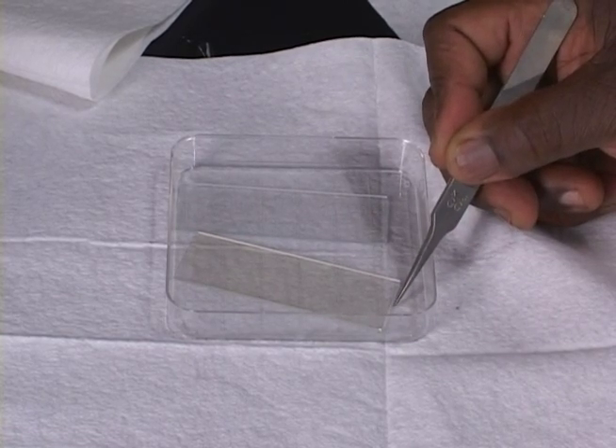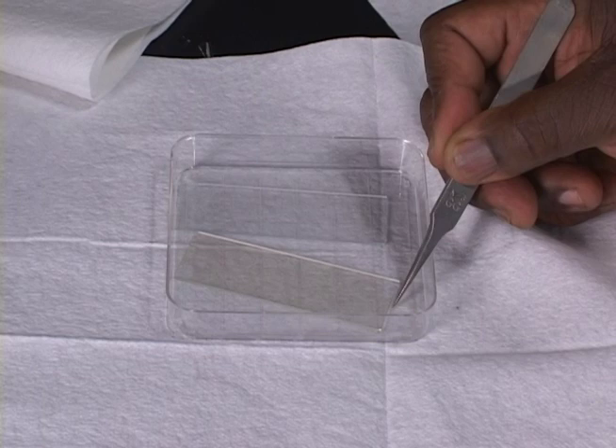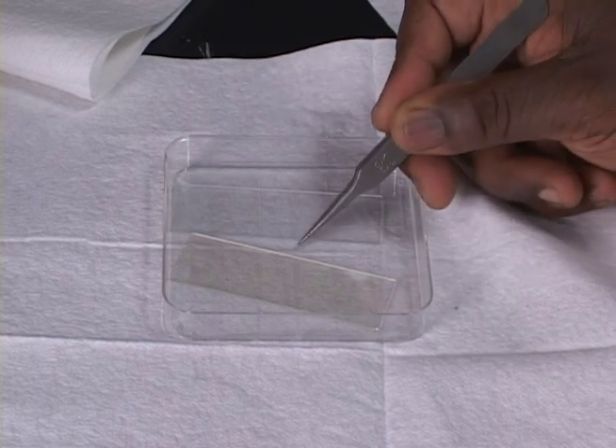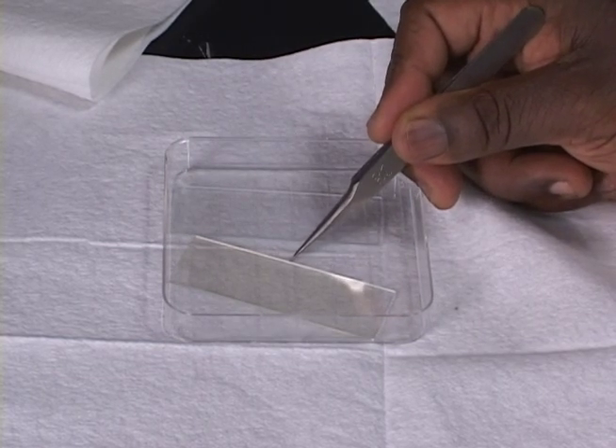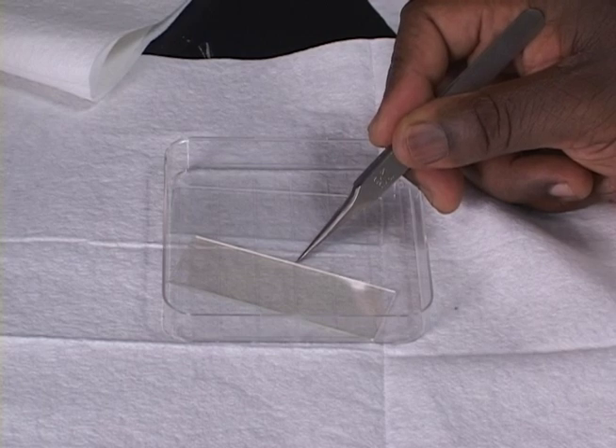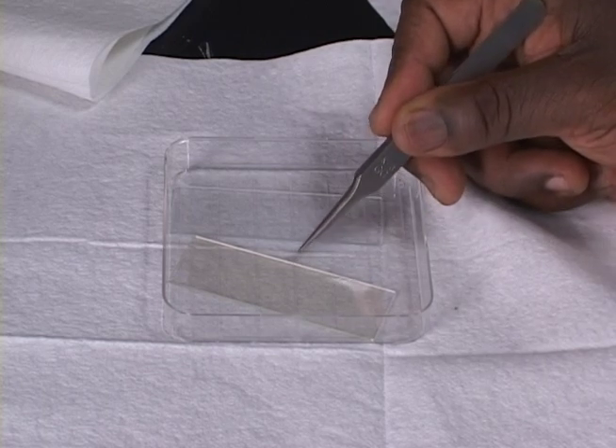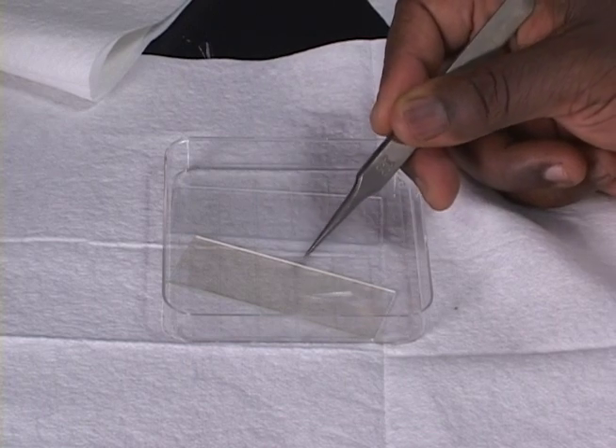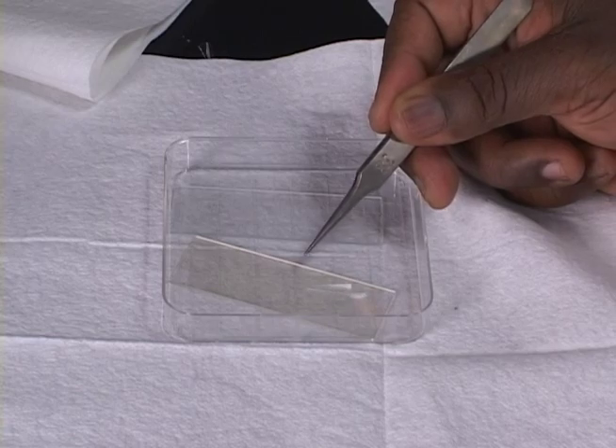And this one, in this case, is AZO, which is known as aluminum doped zinc oxide. It's a transparent conducting oxide. And what that means is that it's just highly transparent, but however, is a semiconductor. And now we can vary the thickness, or we can vary any of the properties based on the deposition condition.